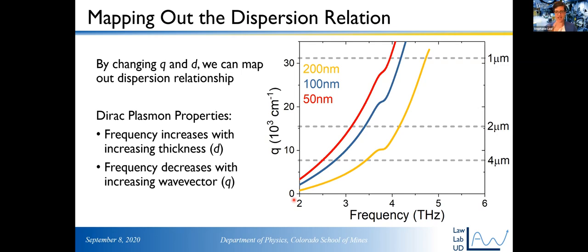Remember before, to excite the volume plasmon polaritons, we put a grating to match the momentum. In this case, we're not gonna fabricate a grating. It turns out we can do something even easier, which is just etch the film into stripes. We're going to set up a standing wave resonance, and the stripe width is going to determine the wave vector. It's the same idea, it's a standing wave resonance, so as you make the stripe wider, you're making the wave vector lower. That's all that's happening here. So we're going to grow films of these three different thicknesses, we're going to fabricate them into stripes of three different widths, we're going to measure their optical properties, we're going to look for the plasmon polariton, and we're going to try to map these dispersion curves, right?